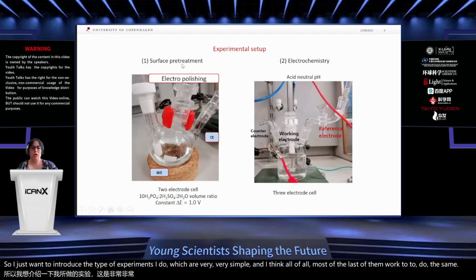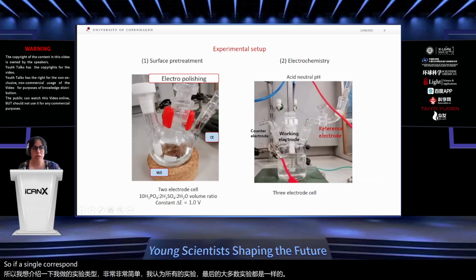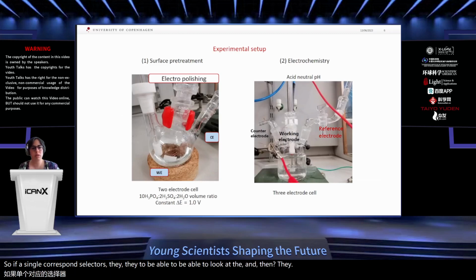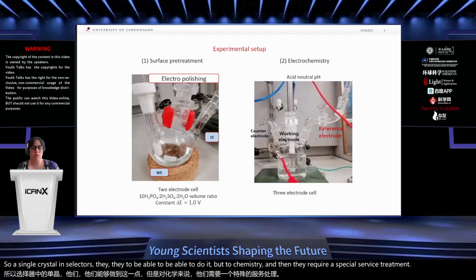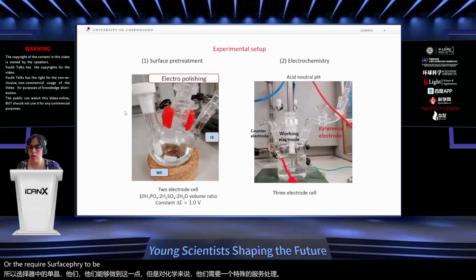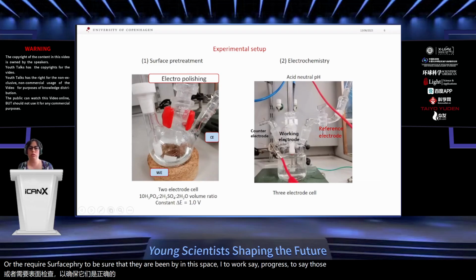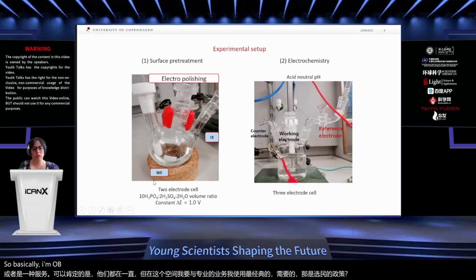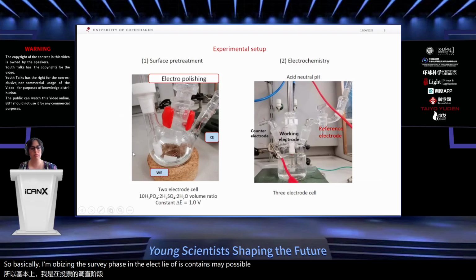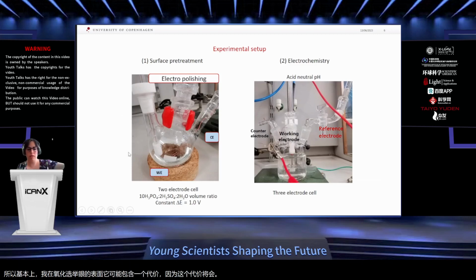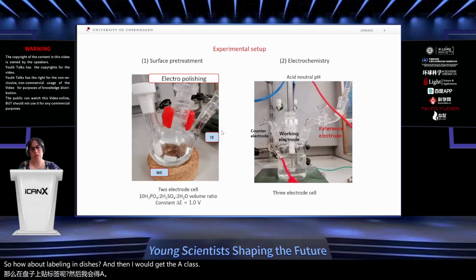Single crystalline electrodes require a surface treatment to be sure that they are ordered and clean before doing electrochemistry. In this case, to work with copper single crystal electrodes, I use the most classical technique, that is electropolishing. Basically, I am oxidizing the surface in an electrolyte that contains mainly phosphoric acid, because the phosphoric acid is going to level the defects, and then I will get a flat, relatively ordered surface.